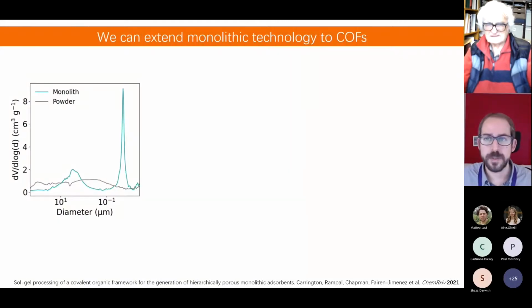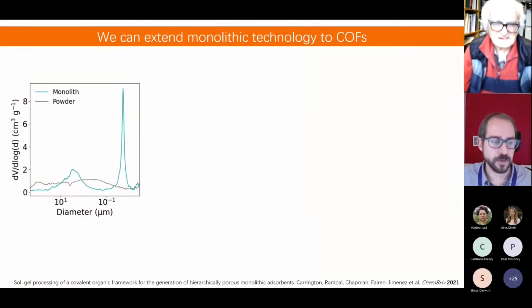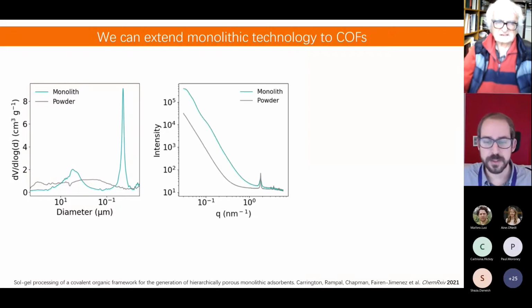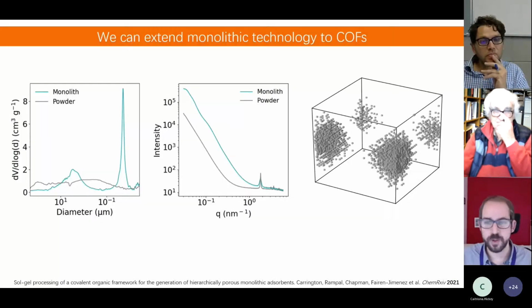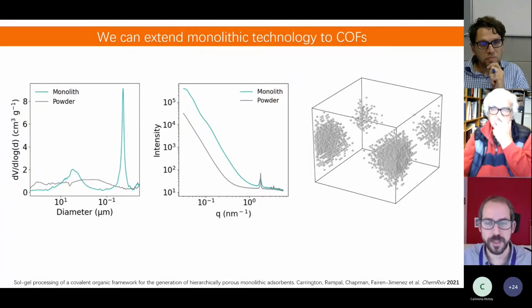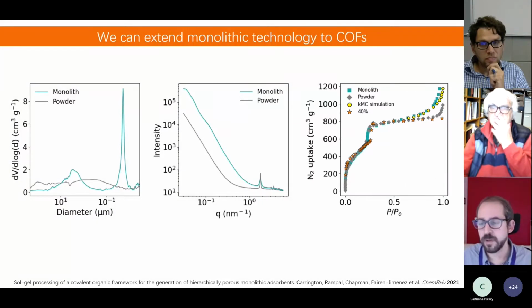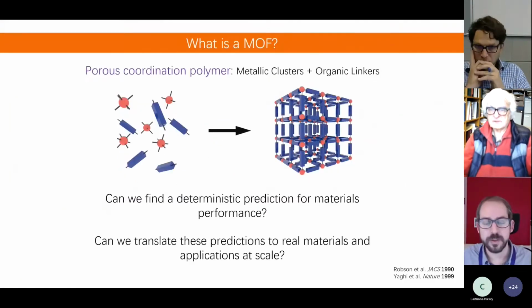We can also develop different porosities, so we can see using SAXS data these different possibilities. So we have seen that we can create different domains, and we can see the existence of some additional mesoporosity in these materials, which is what you can really see here in this representation. At the end of the day, we are going to be able to have materials that we can translate from the simulations to the experiments.